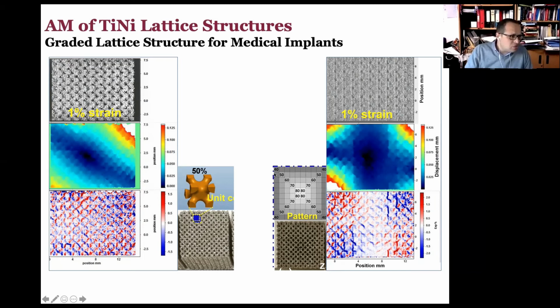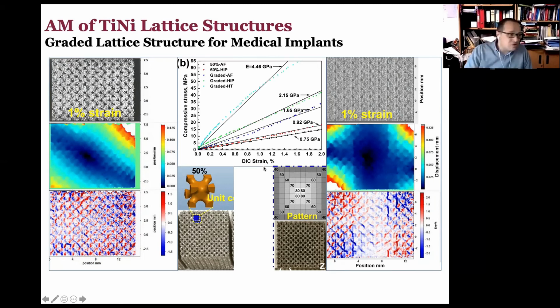But then looking into these materials, one of the things we found was that by playing with the design, we can play with the degree of porosity. We can even generate control in the elastic modulus, achieving very low levels of elastic modulus, approximately 5 gigapascal, which is close to or even lower than the modulus of the bones. This can enable us to tailor the parts of the medical implants from the outside to the inside, to mimic the mechanical behavior of the bone, as in those stents and medical implants.